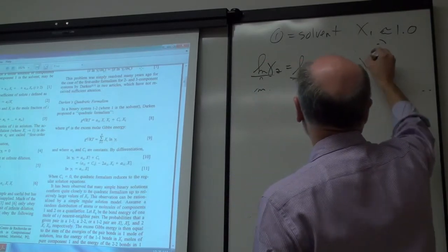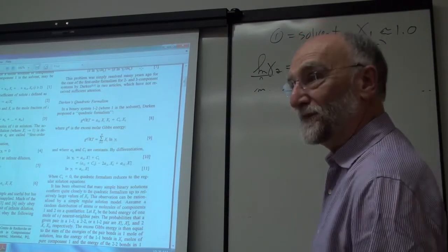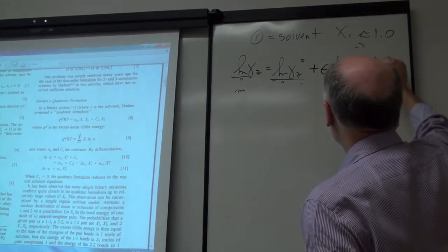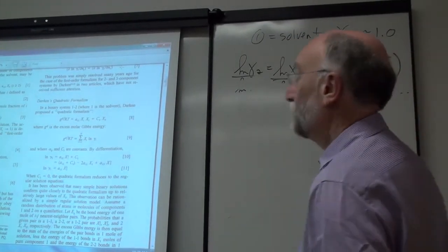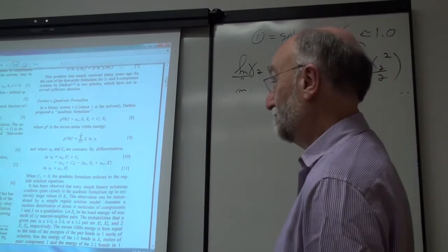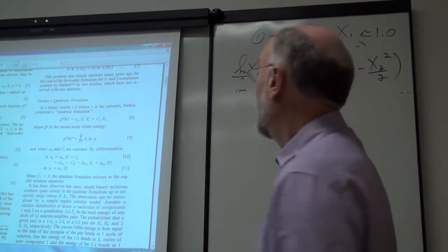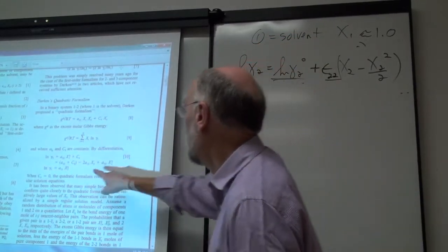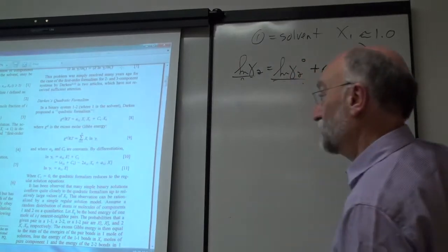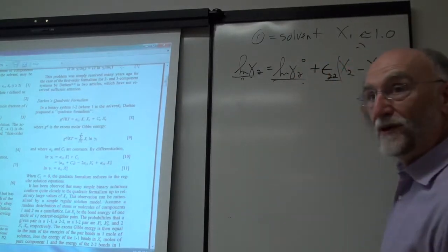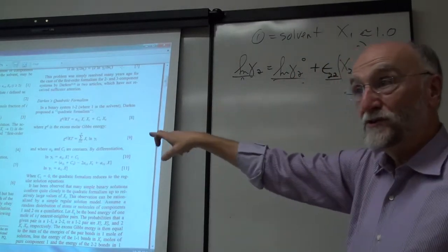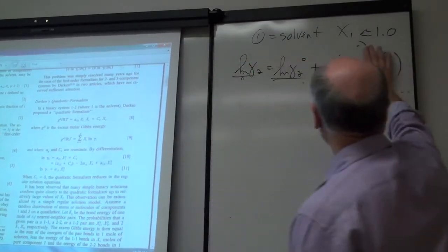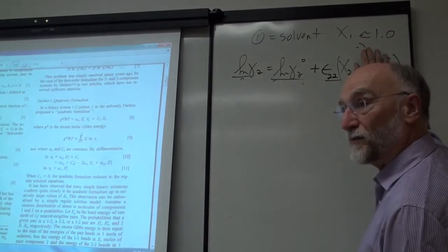This is Wagner's formalism for the binary system. Okay? If you take that, you say epsilon 2,2, x2 squared over 2, you've not introduced any more coefficients. And now this equation is the same form as this. This is the constant log gamma naught, minus 2 alpha 1,2 is epsilon 2,2, and this is epsilon 2,2. Okay, so this equation is the same as Darken's formalism. Now you can see if you truncate this last term, in other words, if you don't put this in, then that's Darken's formalism.